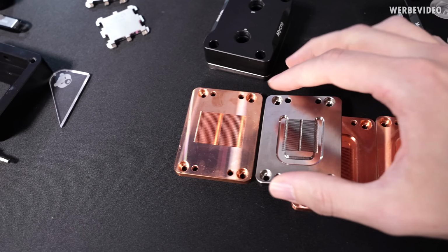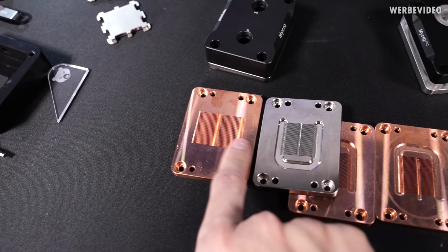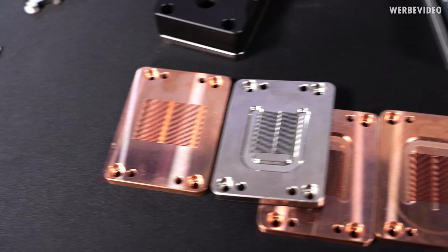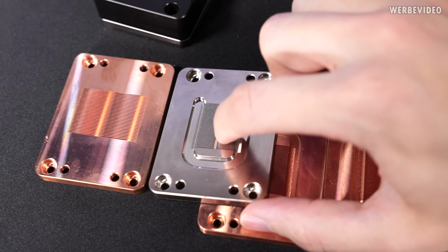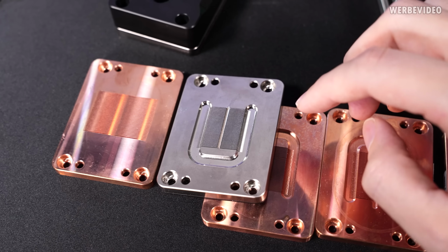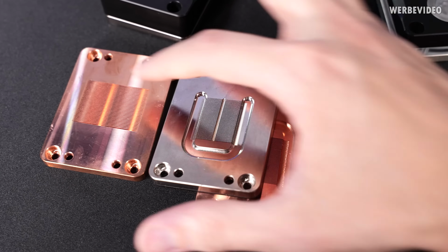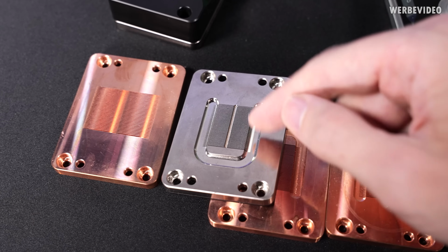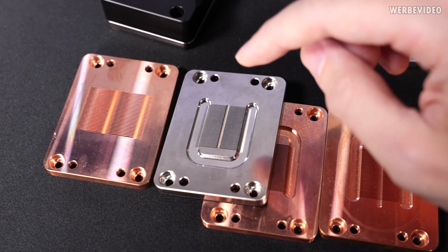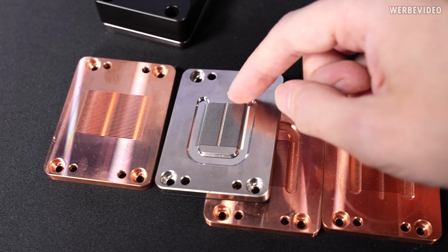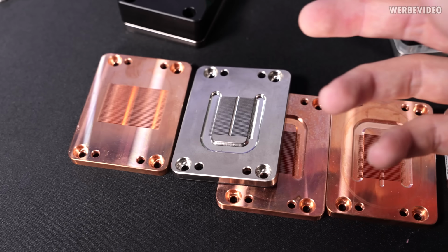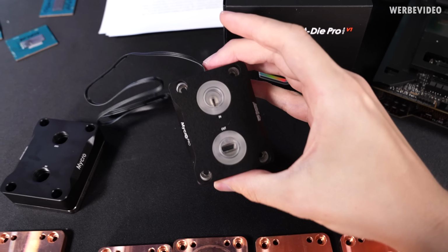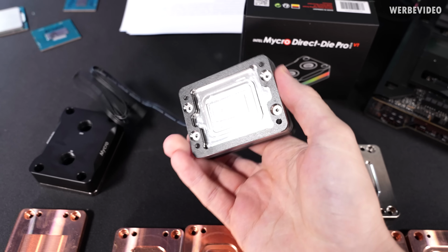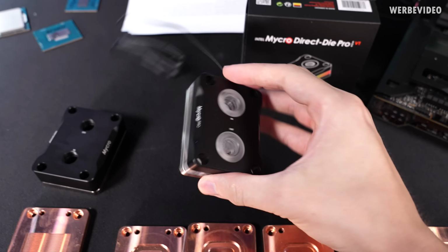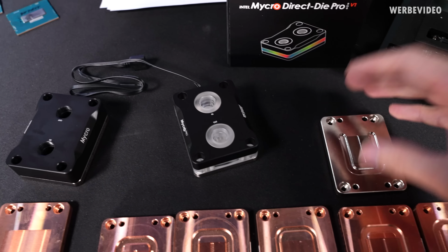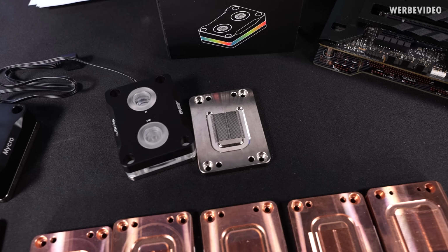And interestingly, if you compare it with the previous one, this is much wider when it comes to just the raw surface area. But if you look at this one, it also has a slot in the center right here, and the fins are a little bit lower. So I think overall the surface area is not much different between these, but with those optimizations, more fins and shorter, you have higher flow rate on this one than on this one, and due to the fins sitting closer together, the resulting performance is just a lot better. So yeah, that is the updated cooler, the Mycro Direct Die Pro. It comes with all the fixes, the improved nickel plating, much better surface area, and features this 0.25 slotting.